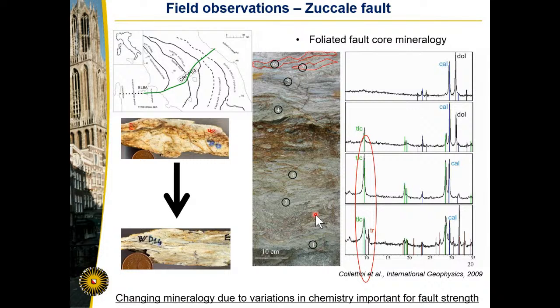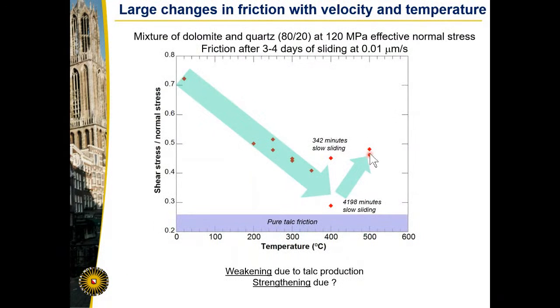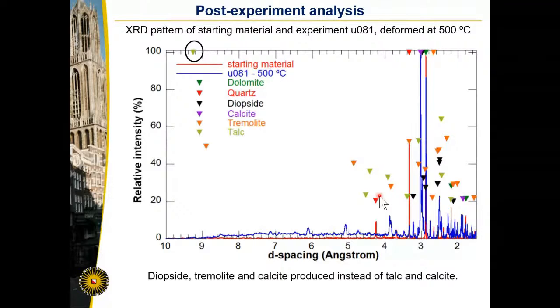Interestingly, in the experiments, I glanced over this, we also see that at 500 degrees, friction recovers again. So we see a strengthening as we increase temperature. So what is the reason for this? Well, that is because at 500 degrees, we are no longer producing talc.